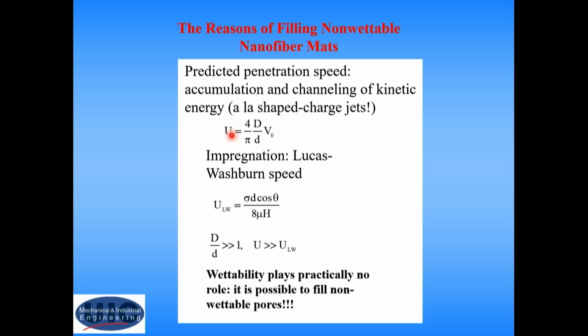Now U here is the velocity of the original penetration of water into pores. And there is a numerical factor in the planar problem, 4 over pi, which is of the order of 1, but there is a ratio of the droplet size, capital D, to the pore size, lowercase d. And this ratio is on the scale of 1 millimeter to 10 micrometers, okay? So the ratio is essentially about 100, or sometimes it can go even to 1,000. So it means that even though you have 1 meter per second approach velocity, water goes into pores with a velocity of the order of 100 meters per second, okay? And this is a tremendous velocity. If you go to 1,000 meters per second, you're approaching the compressibility limit, the sound speed of water.